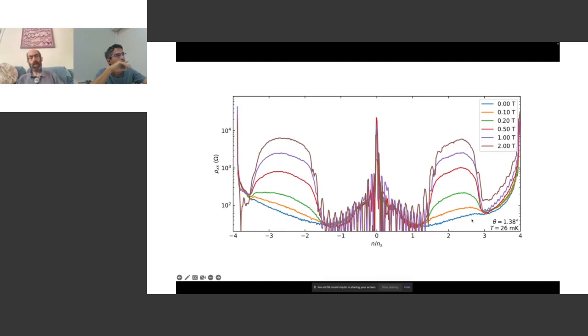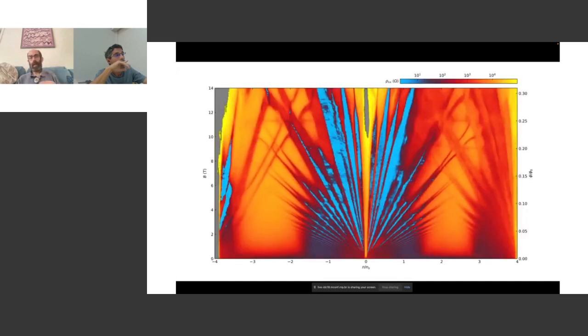And so let's combine the data that I've showed you so far into a color plot in two dimensions, field and density. And so here's the striking behavior. There are all these lines radiating out from the charge neutrality point. These are Landau levels. And then half the Landau levels terminate when we go into this region with magnetoresistance, and the other half, each one splits into two. And then when they cross other Landau levels coming from fully empty bands, there's a rich behavior. Again, I don't have time to go into all of the details, but this is a really striking set of behaviors, and we had no idea why it was happening.